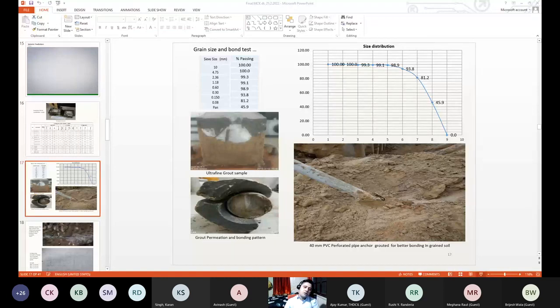This slide I did not want to show, but it is the final criteria. When water is inflowing inside the tunnel, then you have to go with the A and B component, and where the cavity is formed, you have to do this. And it has already been discussed by so many experts. So the gel time will be 55 seconds, and the setting time will be finished within 60 seconds. Two types of polyurethane grout are being used. One is single component, another is double, and there are again two kinds of material, foaming and non-foaming. So you have to select the material the manufacturer is recommending. It is just to study, then you have to go ahead.